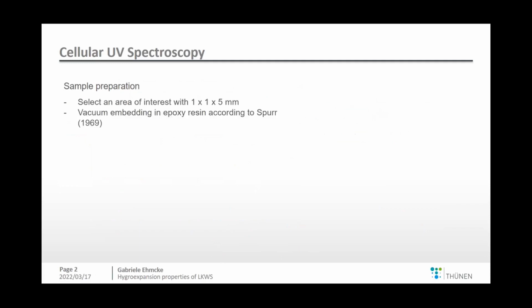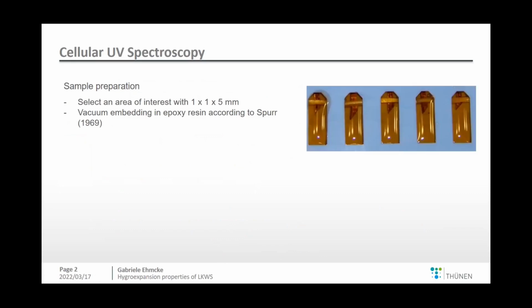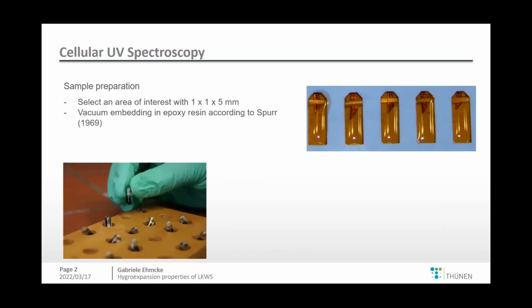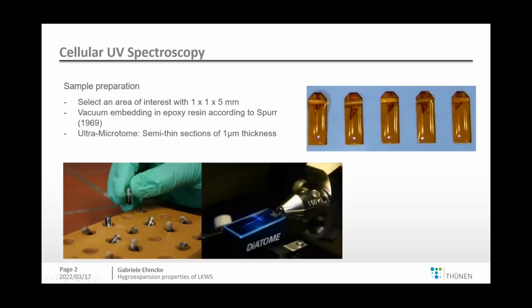And now we have the sample preparation. You already saw some nice pictures in Anna's presentation. Here we have the sample size. It's about 1 millimeter by 1 millimeter in the cross section, and then about 5 millimeter length. And here we have a picture of the vacuum embedding in the epoxy resin according to Spurr. So it's a very mild embedding system. You can use this one, or you use capsules. And then you have to use an ultramicrotome to prepare the semi-thin sections of about 1 micrometer thickness.